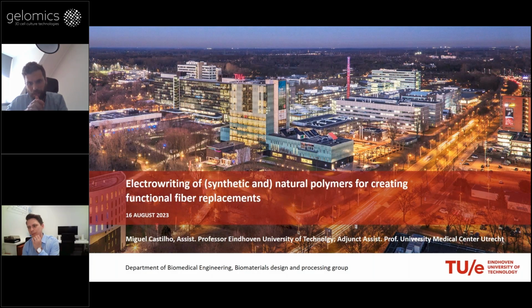Well, the question is coming from one of the attendees. Maybe we can just add that information as well. But from my understanding, obviously in extrusion-based bioprinting, you need to optimize the bioink to display a very strong shear thinning behavior. So you have something that is maybe a gel initially, and as you apply force, the molecules align and it becomes liquid. And as soon as it leaves the nozzle, it solidifies again because the polymer chains, I guess, are tangling up again. And my interpretation of the question is whether this is also an important property for the material to be extruded or printed using MEW.